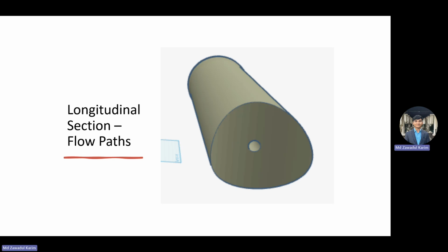Cut lengthwise, you can follow the flow. High pressure feed enters through and travels the full spiral path. As water slips through the GO nanochannels, it's collected by the permeate tube and exits at low pressure. The remaining concentrate leaves at the far end, carrying rejected dyes away.